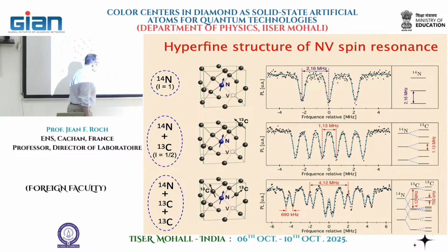And if I continue like that, I can add another nucleus, a second nucleus, which is maybe at a longer distance. This coupling will now produce another 2 couplings like that, et cetera, et cetera. And as soon as my lines are narrow enough, I can try to distinguish all these pairs and try to map where they are located in the lattice.